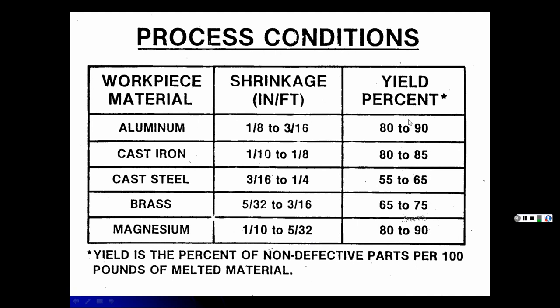And then it just shows you yield point. Again, what's our lowest? Is cast steel at 55. Brass 65, magnesium 80 to 90, aluminum 80 to 90, cast iron 85. It's amazing the difference between, well, I guess that's why they call it cast iron. It casts so well. Steel does not. Cast steel does not. So yeah, you look at that, and that has the most, 1/4 of an inch shrinkage. Shrinks the most. So, and your yield percentage is really bad.